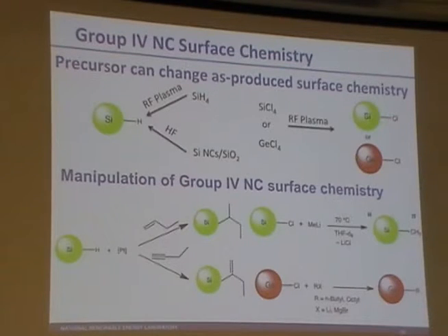And so the surface chemistry of quantum dots, as we all know, is extremely important, and this is one of the areas that I'll be focused on significantly over the next couple of years. I've already shown that one can do traditional organometallic reactions at the surface, such as a simple salt metathesis reaction, where you take methyl lithium and add that to a silicon chlorine bond, you eliminate lithium chloride and get your silicon methyl groups. I will say that this reaction is very messy.